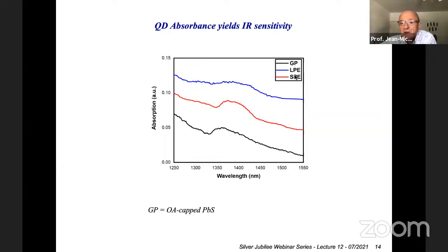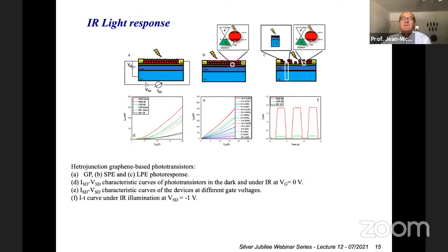And like I was saying, we worked on the ligands. So we used the formamidinium lead iodide ligands to replace the oleic acid ligands, which are technically what is used when you purchase these lead sulfide, or when you fabricate lead sulfide by current techniques. So we made a ligand exchange, and here is just a comparison between the liquid ligand exchange versus a solid ligand exchange. So one is by immersing the quantum dots into a liquid, and the other one is just by making the substitution in situ on top of the transistor.